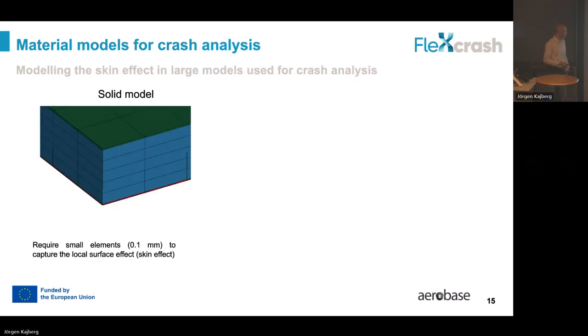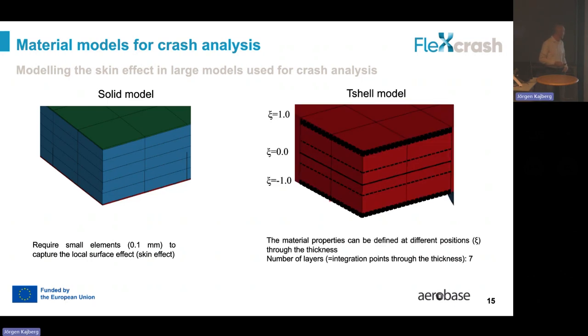What we have also done is to be able to resolve this very thin layer of small grain size in the component. If you use a solid model, for example, it becomes a very small element. The green area here, you can see that it's elements that are 0.1 millimeter. The time step will be extremely small in an explicit crash analysis. So what we propose is that we use something called thick shell, where you can define your material properties in different layers. Then you can easily include the skin effect.